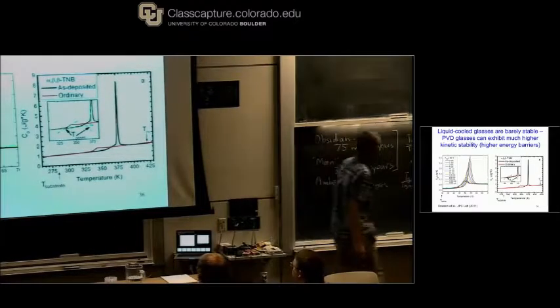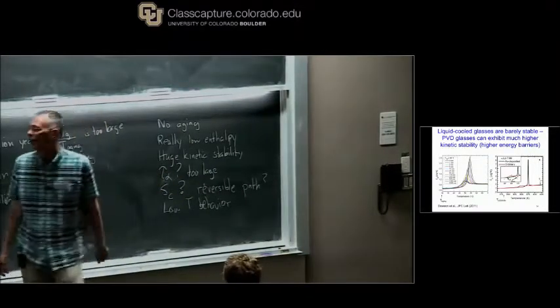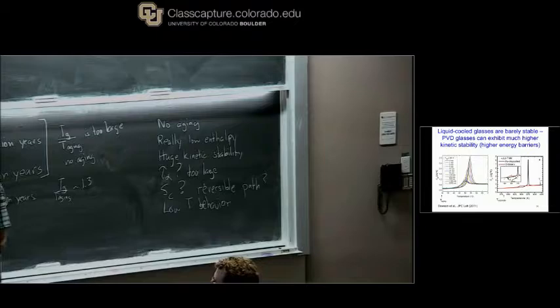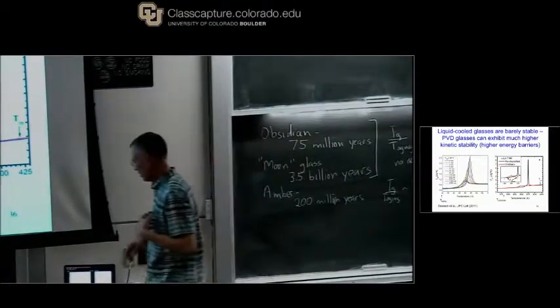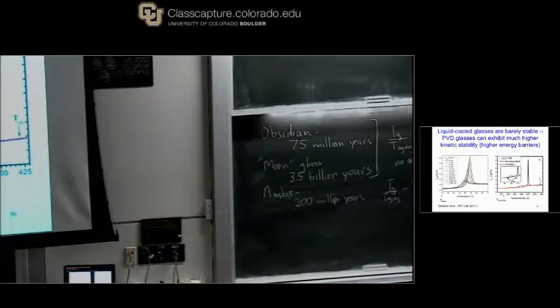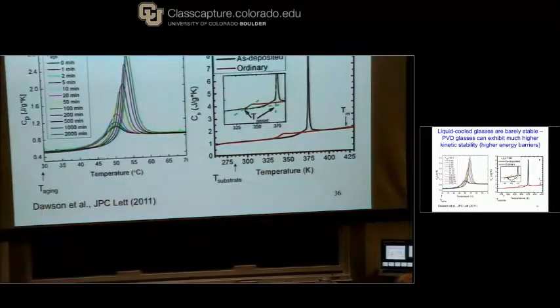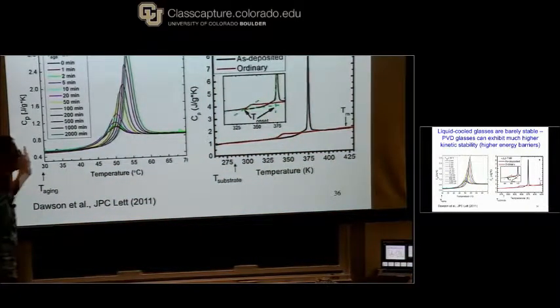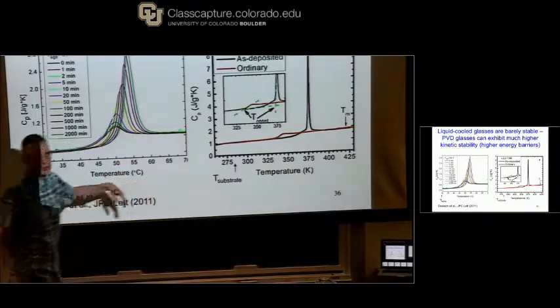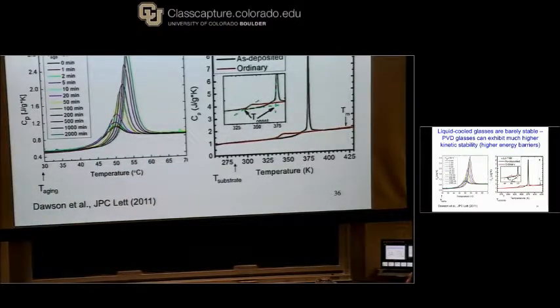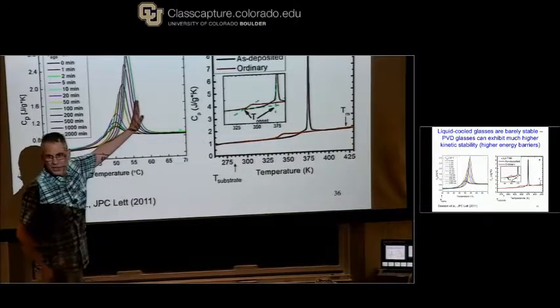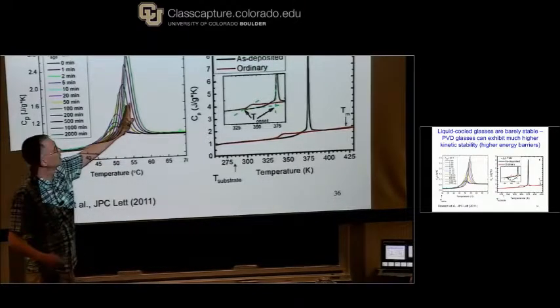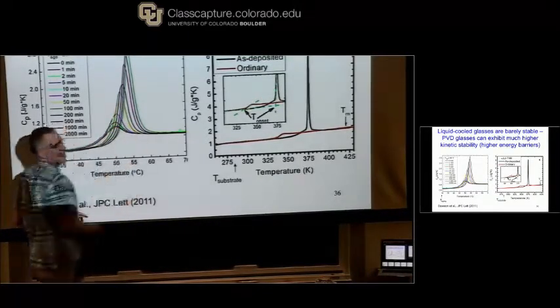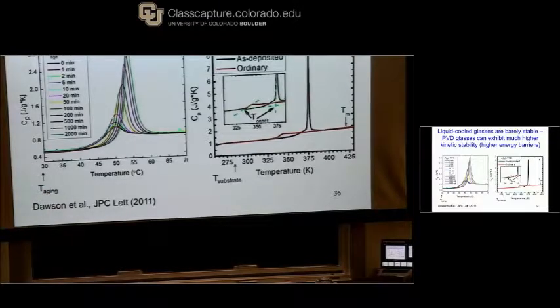I want to get to this question about huge kinetic stability, and can we say anything about tau alpha? In fact, the kinetic stability is huge, and let me show you that in the following demonstration. I showed you curves like this yesterday. This is what happens in a differential scanning calorimetry experiment. You cool a glass, and then you age it for different periods of time before you reheat it. And the longer you age, the more the curve shifts to the right. That's increasing kinetic stability. The bigger the peak gets, that's the dropping enthalpy of the sample.